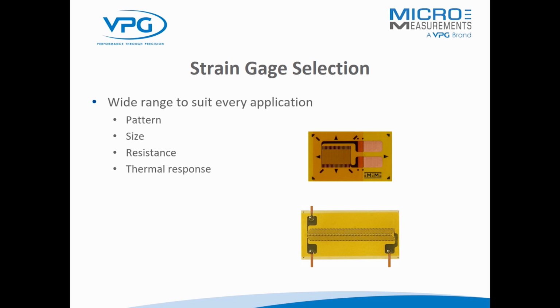The second gauge that's on this slide, the one down below, is a dual shear pattern, and this one is specially designed for testing the shear modulus of composite materials when you've got Iosipescu type specimens. This test was developed many years ago, where you take a composite and you shape it so it looks about like a bow tie. You basically cut notches into it, and this gauge is designed to cover the entire distance between the notches in one of these shear modulus coupons.